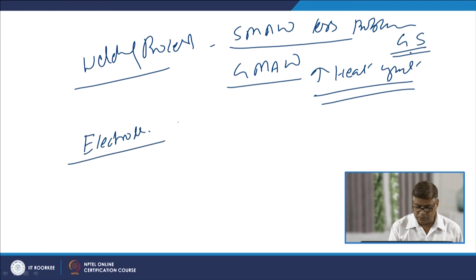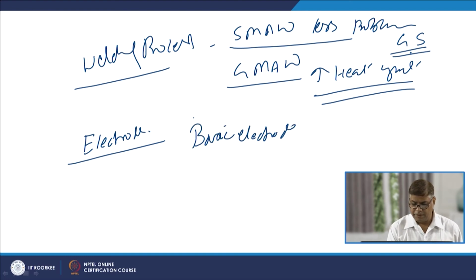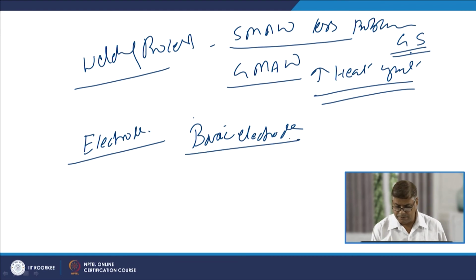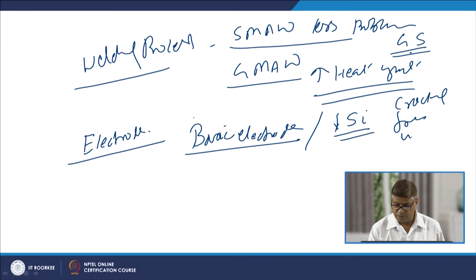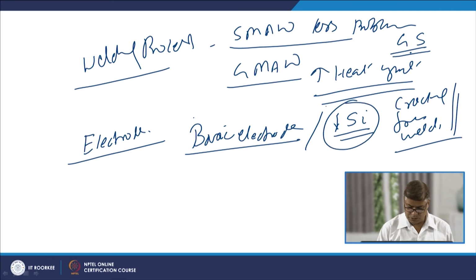Next is the kind of electrodes which are used. So, for electrode classification, we prefer to use the basic electrodes for effective shielding in case of SMAW, and the electrode should have a lower silicon content. Silicon content in the electrode is kept lower for producing a crack free weld metal. So, in order to reduce the cracking tendency, this has to be lower.